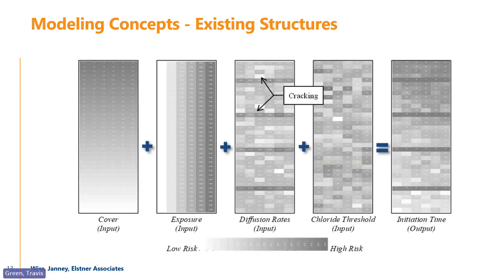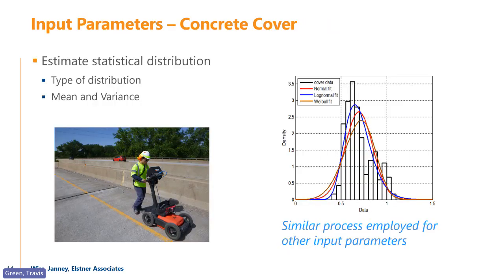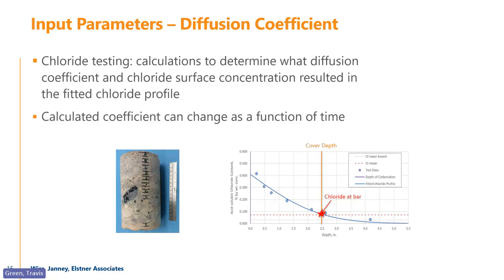So this is an XY, kind of a plan type explanation of that. So how do we do that, right? So we go and get physical data, usually with GPR, and it's verified via openings, and we curve fit the concrete cover data, right? And that's not always a normal fit. That can be a log normal fit of the cover data, and so we use that as part of the Monte Carlo simulations. We then like cores. Some people like powder samples. I think Wiss Janney's opinion is generally that the powder samples can cross contaminate, and so we do these slices of these cores, and we use those.